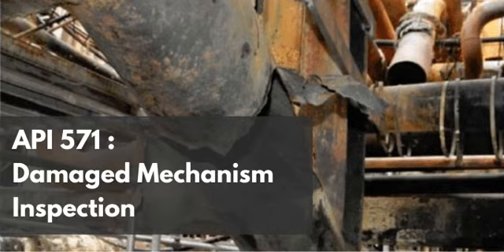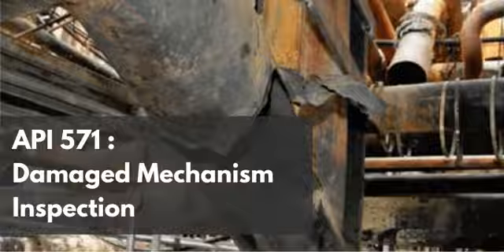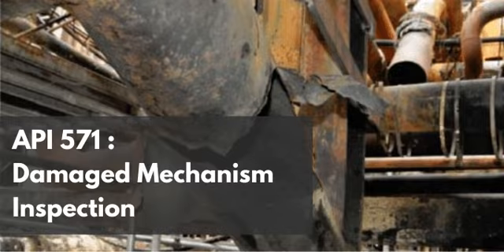The data details a specific phenomenon that drives this catastrophic snapping. It details what it calls catastrophic carburization. Which is a terrifying phrase. It really is. It states that in advanced stages, the metal undergoes a volumetric increase. The forming carbides cause the surrounding metal to literally crumble due to this increase in volume, resulting in significant metal loss over time. This comes down to pure physics and crystallography.